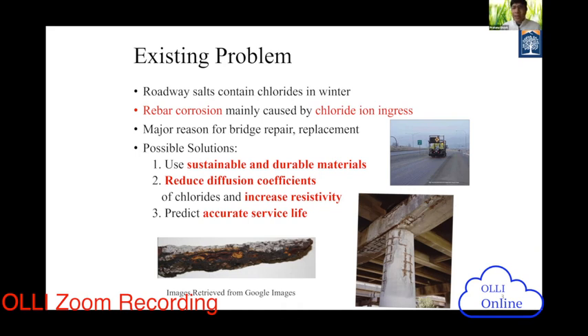The second part we can think about is that we need to reduce the diffusion coefficients of chlorides. So what does diffusion coefficient mean? We know that chloride is diffusing through the concrete from the top of the slab, and then it starts to ingress through the concrete, and after a certain amount of time it starts to attack the rebar, basically the reinforcement within the concrete. So diffusion is the mechanism through which chloride is going through.